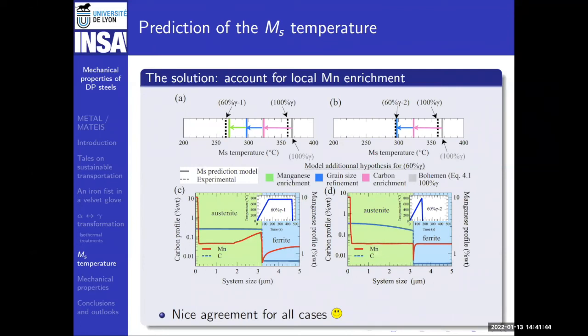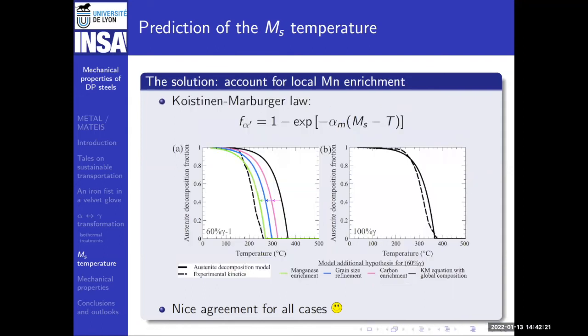So to make this model reach the actual true line, we have to account for the actual manganese content, not the one given by equilibrium, but the one that was given by the previous model at the interface. So we have to enter not the global manganese composition of the steel, but the local composition at the interface. And if we enter this particular composition in the model, then we can make it fit the true martensitic start transformation. So, accounting for the local composition of manganese that we took from the previous model, we could get a nice agreement for martensitic start temperature.